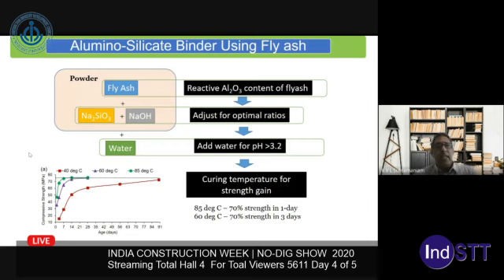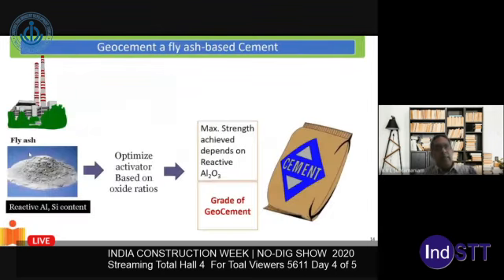Now, from there, we are able to collect fly ash from different thermal power plants and optimize the activator for this, and be able to produce cements which give us consistent strength and consistent properties. And this is done following the characterization of the fly ash that is obtained from these thermal power plants. This cement would produce a geopolymer which gives us consistently high strength and high durability.